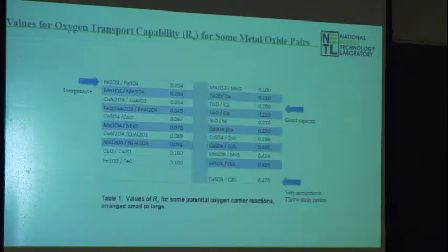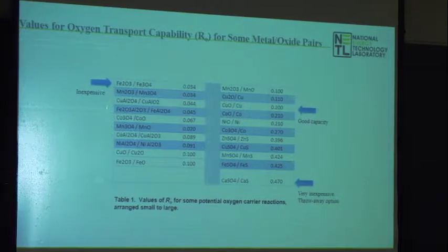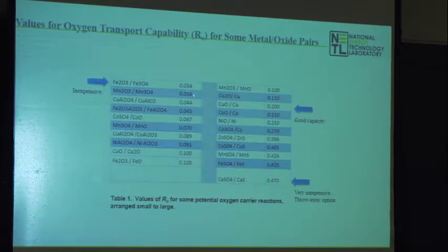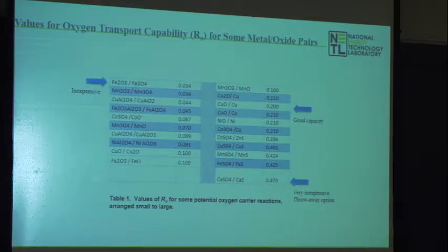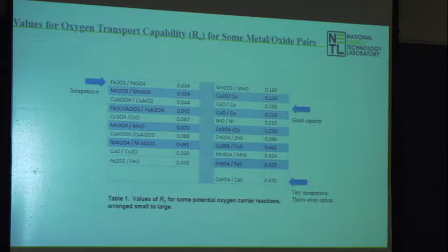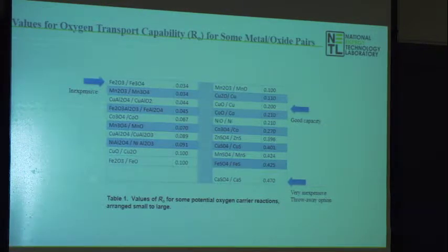All right? Let's take a look at how big that is. For iron being reduced to its next lowest oxide state, hematite to magnetite, about 3.4% of the mass of the iron comes off as oxygen. So you think, there's not much oxygen available. You start thinking, I've got to circulate a lot of material around to supply oxygen. You're right. Maybe I should look at something else.